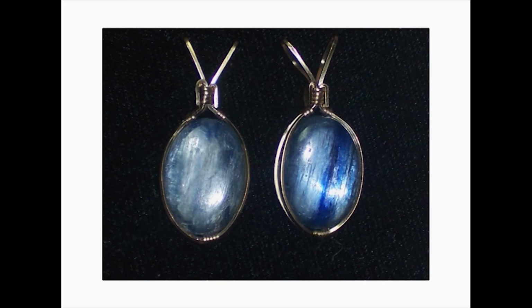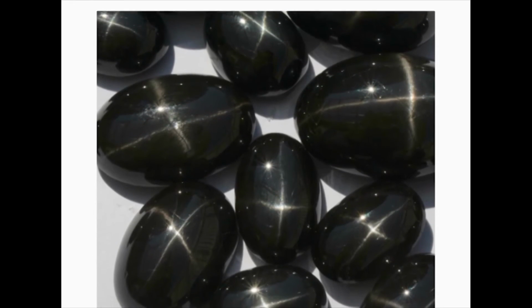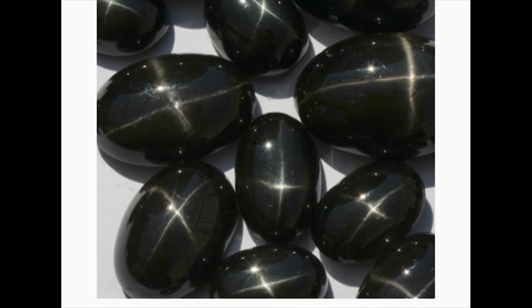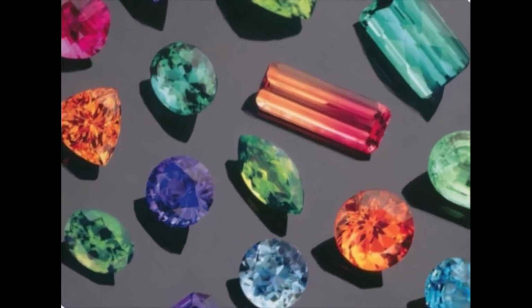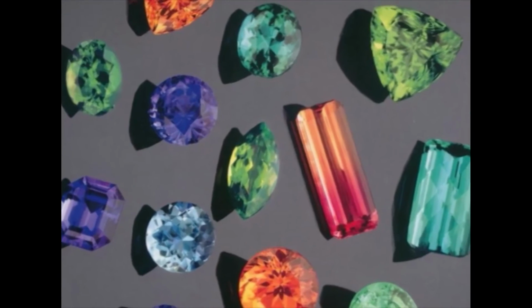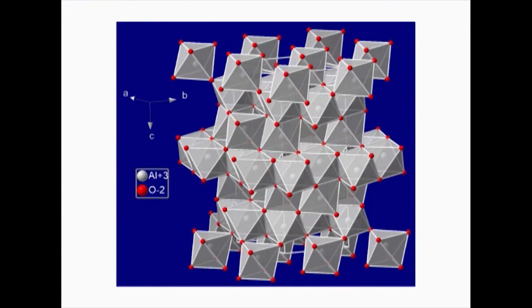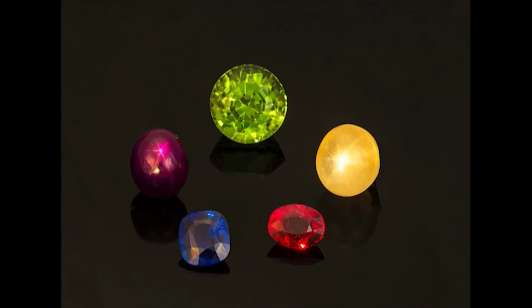Asterism. The ability of a gemstone to show a star is called asterism. Asterism is caused by the dense inclusions of tiny fibers of foreign minerals in gems. Generally, these inclusions are the reason for the reflection of light and form a wavy star-like formation which moves around when the mineral is rotated. The inclusions must be long, very thin, needle-like, which is called rutile. Asterism is produced when needles intersect each other in multiple groups.